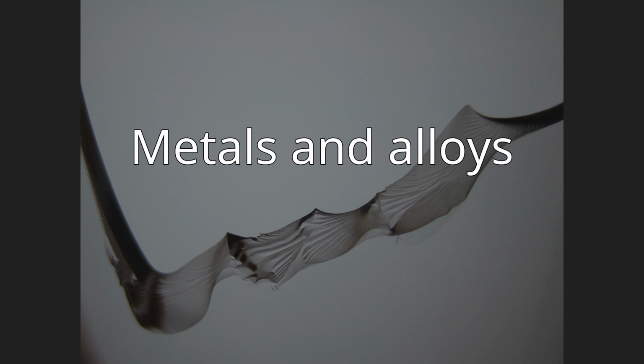Metallography is a routine technique for examining the microstructure of metals, but can also be applied to ceramics, glasses, and polymers. SEM can often be critical in determining failure modes by examining fracture surfaces. The origin of a crack can be found and the way it grew assessed to distinguish, for example, overload failure from fatigue. Often, however, fatigue fractures are easy to distinguish from overload failures by the lack of ductility and the existence of a fast crack growth region and a slow crack growth area on the fracture surface. Crankshaft fatigue, for example, is a common failure mode for engine parts. The example shows just two such zones, the slow crack at the base, the fast at the top.